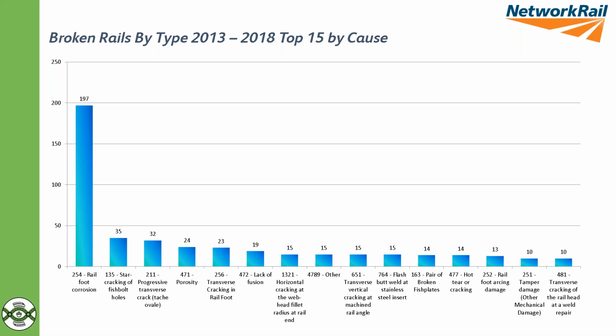But what it does mean, certainly from a type of break and cause, is that rail foot transverse defects or pitting, whatever you want to call it, has become an increasingly big problem. Perhaps not in total numbers, the numbers have been pretty much the same, but as a percentage contribution to the overall number of breaks, a very sizable target there, and something that particularly tends to affect our higher speed, higher tonnage lines.